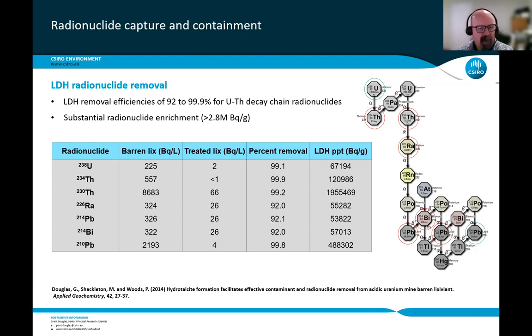We've got the activity in becquerels per litre in the second column of the barren lixiviant. Then we've got the treated lixiviant activities in becquerels per litre. As I said, the percent removal. So as I said earlier, anywhere between about 92 and about 99.9%. And then within the layered double hydroxide precipitate, we have the activity in becquerels per gram. So some very large activities, particularly there for thorium-230.